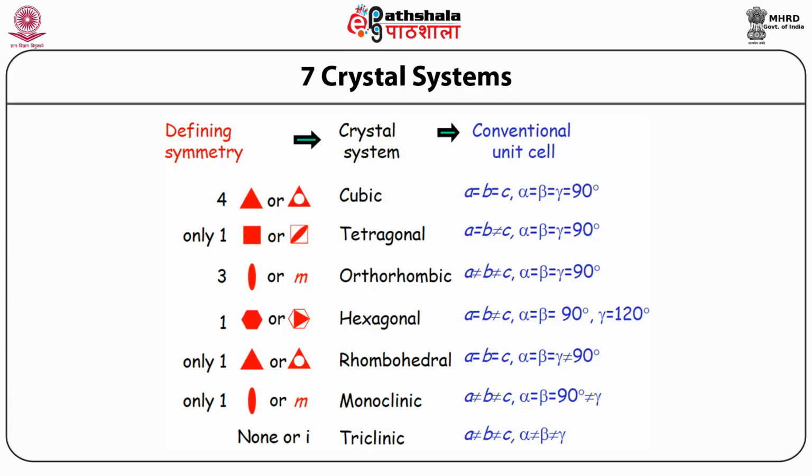The FCC unit cell has 4 lattice points, implying that it has 4 primitive unit cells. Likewise, the reason why we don't have a face-centered tetragonal cell is that we can always have a smaller unit cell inside, which is a body-centered tetragonal with similar four-fold symmetry.